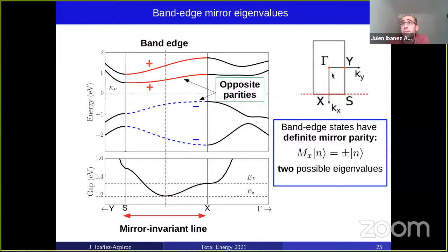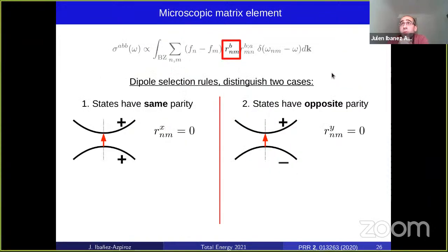So let's keep this in mind and consider now the expression for the shift current matrix element, and more in particular, the dipole term. One can distinguish two dipole selection rules depending on the relative parity of conduction and valence bands. When states have the same parity, the matrix element containing the mirror index is forced to vanish. That is, the dipole term Rx is forced to vanish. Whereas if the states have opposite parity, then the matrix element without the mirror index, in this case Ry, is the one that vanishes.